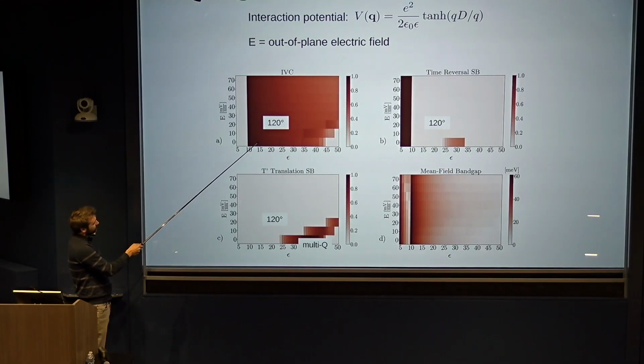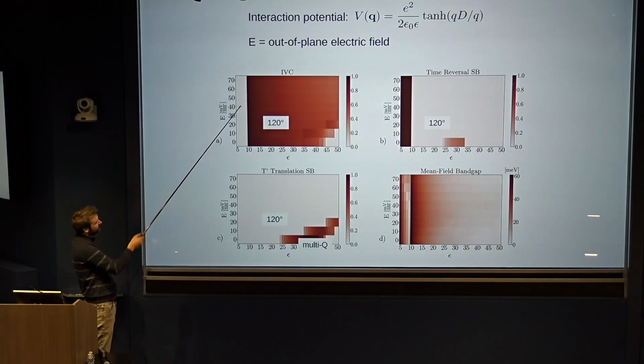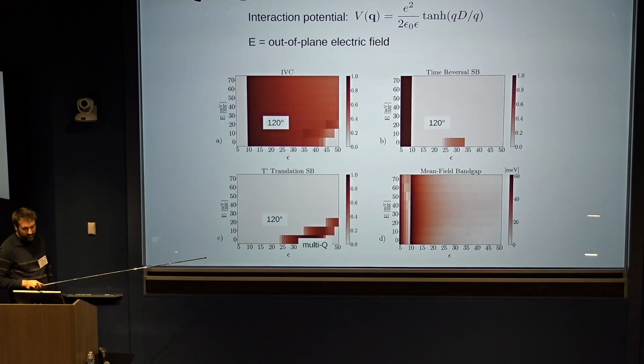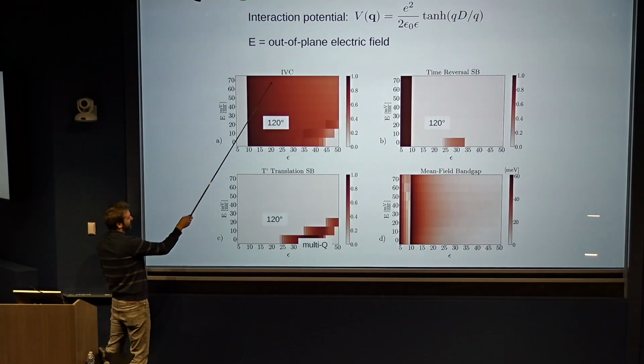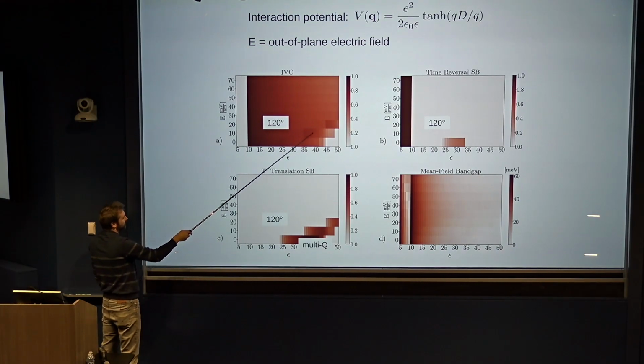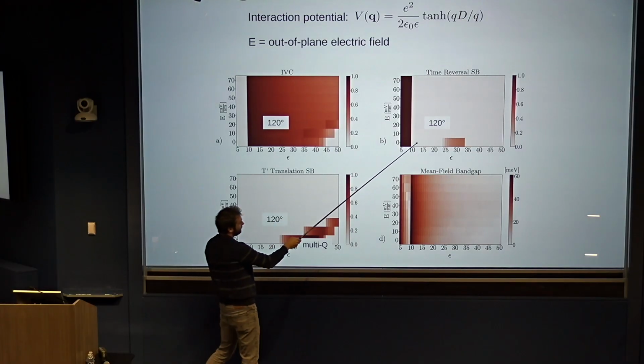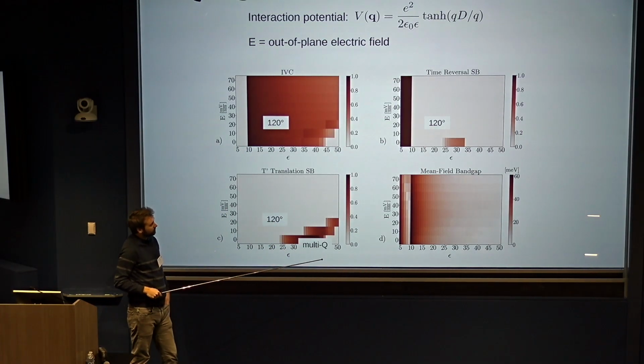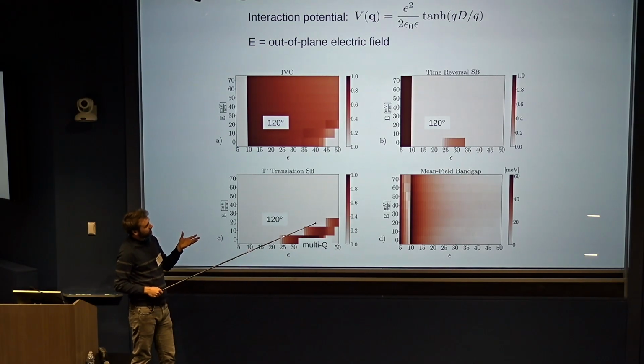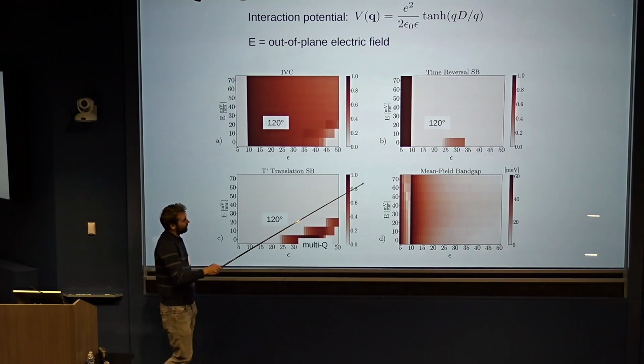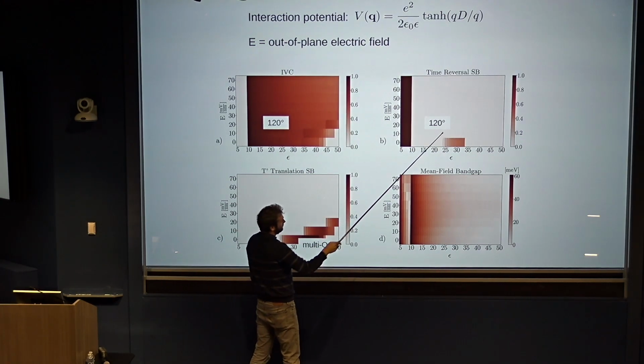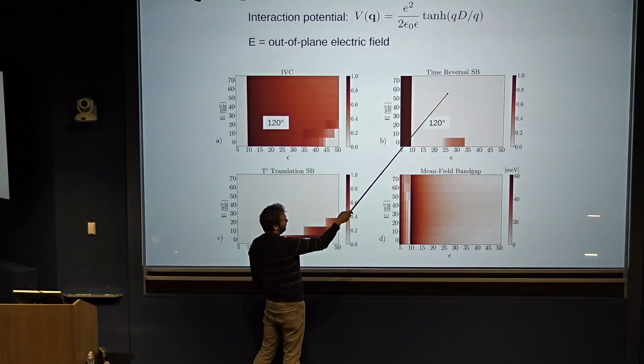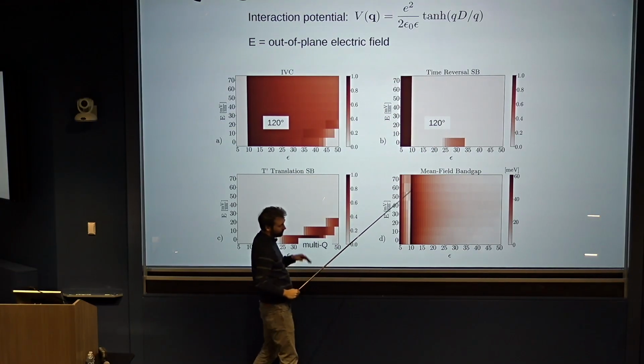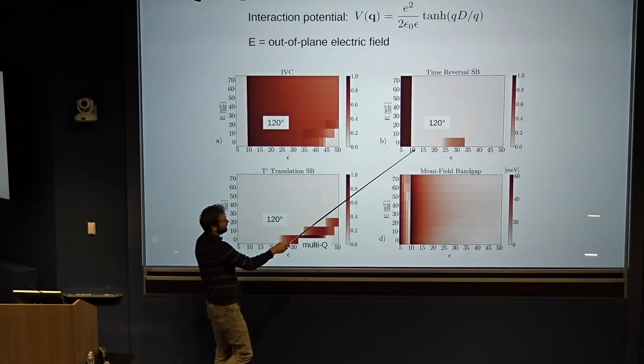On the top left plot, I named it the IVC order parameter. But because of the spin valley locking, this is really the size of the in-plane magnetic moment. You see there's a large region where this is non-zero, almost everywhere in the phase diagram. The top right figure shows a time reversal breaking order parameter, but it's not the Kramers time reversal, it's a different type of time reversal, which only flips the out-of-plane components of the spins. In most of the phase diagram, this order parameter is 0, which means this symmetry is not broken, where you have purely in-plane spin order. So this 120-degree state preserves this symmetry.